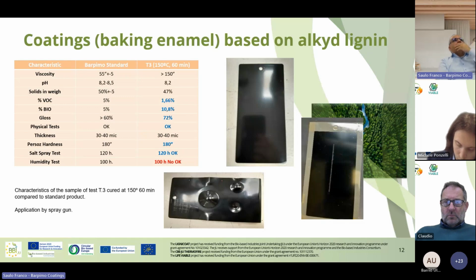In this case, you can ask, so why do you achieve only 10.8% of bio content? This type of coating has a high filler content, so it's a lot of mineral fillers in the formulations. And these fillers are not considered bio. So this is why we have a very low content of bio raw materials in the formulation. Not because we were not able to introduce more bio content, but because of the type of formulation. But for this type of formulation, 10.8% is quite good. The gloss we were able to achieve a little higher. It's a good thing.